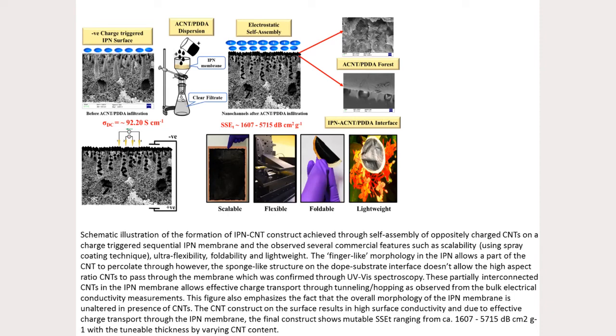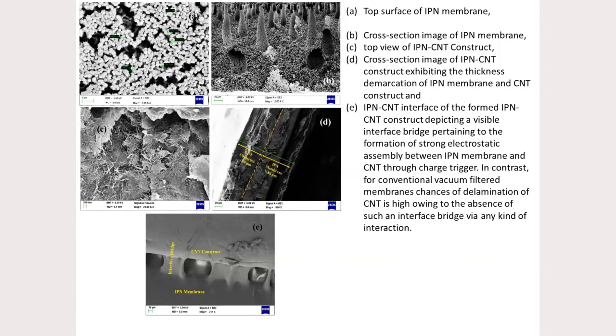So these constructs, which can be easily made by electrostatic assembly, have numerous advantages. As you can see, the DC conductivity is about 92 Siemens per centimeter, and the shielding effectiveness is very high, which I'll show you in a minute. So these are the porous structures, and if you carefully observe figure D, you can actually see the IPN membrane and the CNT construct over the IPN membrane obtained using electrostatic assembly.